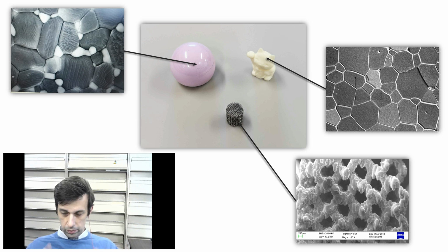For the trabecular titanium at the bottom, the structure itself is this sponge of titanium. And if I say that it's made of titanium, I'm not wrong, but people can imagine a block of titanium, and saying just titanium does not help us to predict the properties. Even to say titanium alloy, this is titanium 6 aluminum 4 vanadium, does not help us to predict the properties of the sponge, because it's much softer than a pure 100% block of titanium would be.